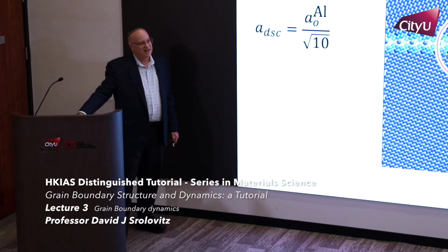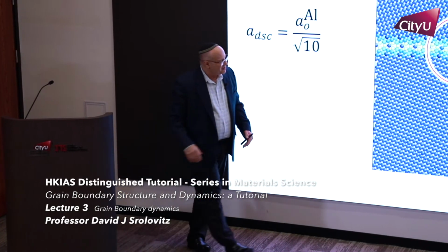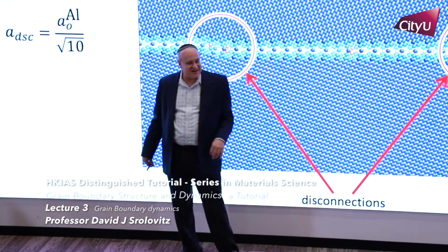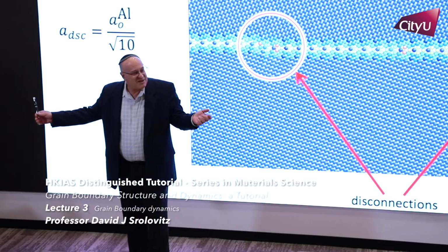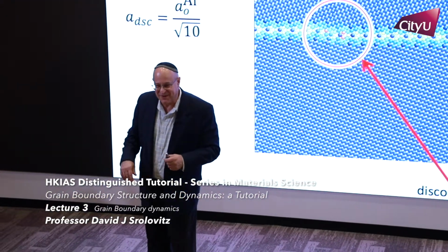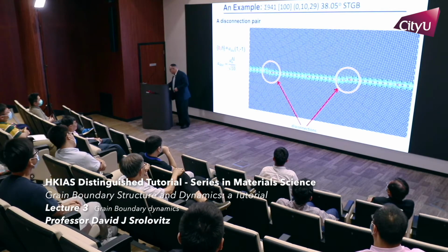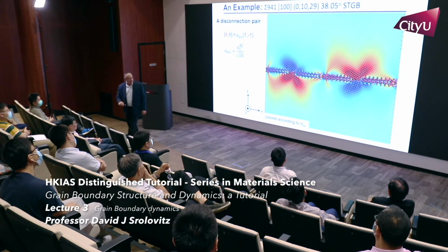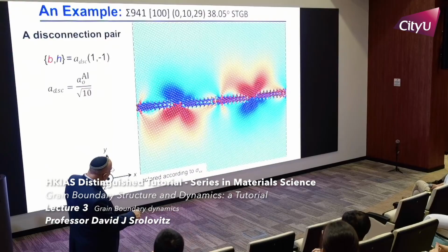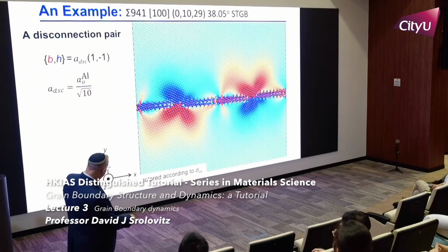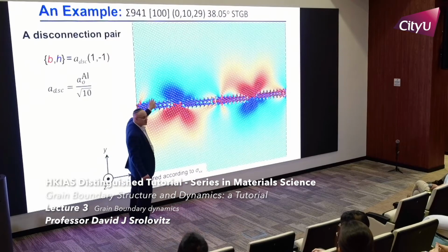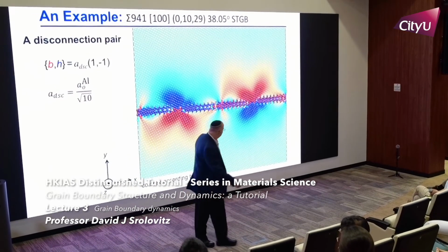Now, with a complicated structure like this, don't these things, with these really tiny Burgers vectors, these really tiny step heights, how could that possibly matter given how complicated this boundary is to begin with? Well, if I look at the stress field associated with this grain boundary, you have this very fine scale stress, associated with the details of the sigma 5 cores and the secondary grain boundary dislocations.